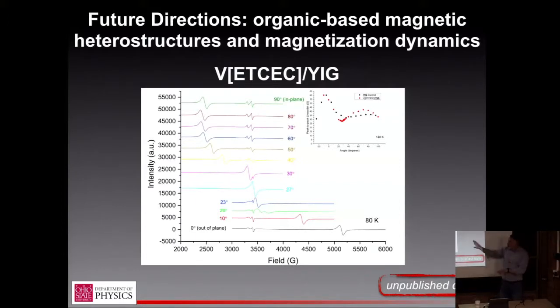And then ultimately, we'd like to come back to the beginning of my talk and actually do spin pumping experiments. But what's the thickness of your layer compared to the distance between centers of magnetism? Well, the YIG layer in this sample I think was 20 nanometers, and the V[ETCEC], it's tough to get an exact measure, but say 50 nanometers or something like that. How far? Okay, and your vanadium centers are? Oh, angstrom, yeah, just a few carbon atoms apart. So very, very thick. It's a bulk material, bulk film.